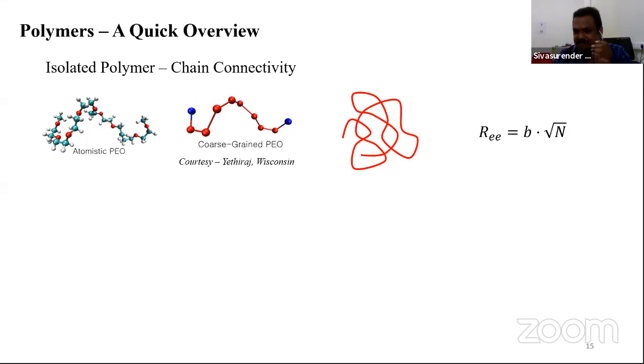And now if you look at the size and shape of this polymer, it reflects the trajectory of a simple Brownian particle, like a simple diffusion motion, where now your time is replaced by the number of monomers that you have, right? So the shape of a polymer in equilibrium without any interaction resembles the trajectory of a Brownian particle. And hence you can define the end-to-end distance of the polymer via the monomer distance, which is the bond length, multiplied by the root of the number of monomers, right? If it is completely stretched, you would expect this to scale directly with n, but because of this random walk, you have the scaling with root n, the root of the number of monomers.